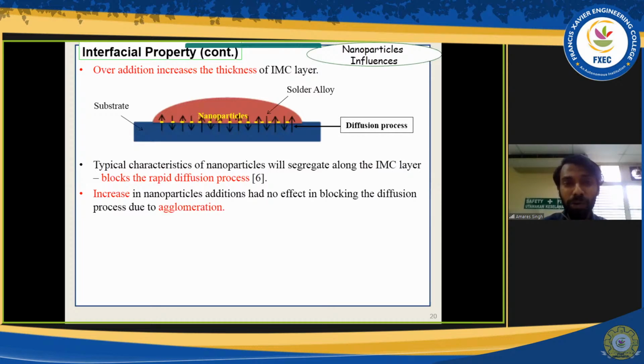But if there are no nanoparticles, there is free movement between the solder's element and the substrate. Therefore, at high temperature soldering or even at low temperature soldering, we will produce a higher or thicker intermetallic compound layer. However, again, we need to preserve a small amount of nanoparticle addition. That means if you have a high weight percentage, like I said earlier, it will go to the edge of the motion. That means there's still considered as no effect in the center. The elements can still move freely without any blocking of the diffusion. So we have to maintain a small weight percentage of addition.